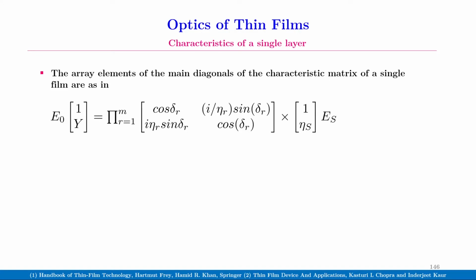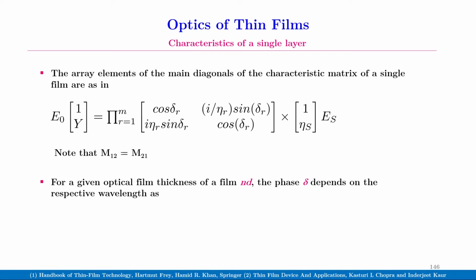We now try to understand the characteristics of a single layer of thin film on a substrate. The array elements of the main diagonals of the characteristic matrix of a single film are given by this expression. Note that M12 equals M21. For a given optical film thickness Nd, the phase δ depends on the respective wavelength as δ equals 2π Nd over λ0 times cos α times λ0 over λ.